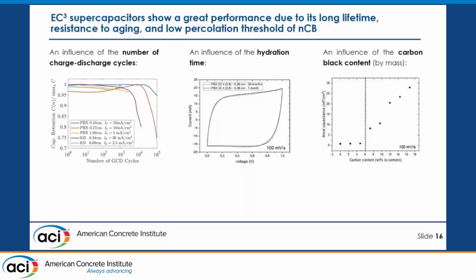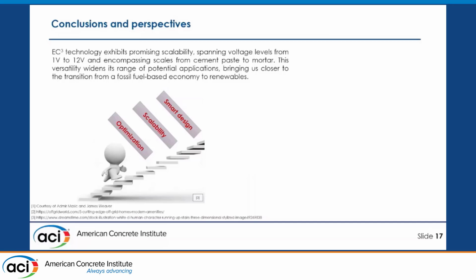And then I'm showing the percolation threshold, which is needed to obtain that capacitance and energy storage functionality. It's slightly higher than when it comes to just conductive functionality, but still it's low. So here I hope that I showed and delivered the message that this EC3 technology exhibits promising scalability, spanning from 1 volt to 12 volts and so on, from cement paste to mortar.